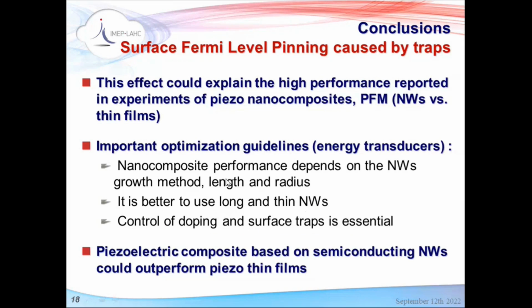So I arrived at the conclusions. I hope I convinced you that the surface traps and this Fermi level pinning could explain the high performance reported in experiments of composites, but also could explain recent results on piezoresponse force microscopy. Then all these models gave us important optimization guidelines that could be used for sensors or energy transducers in general.